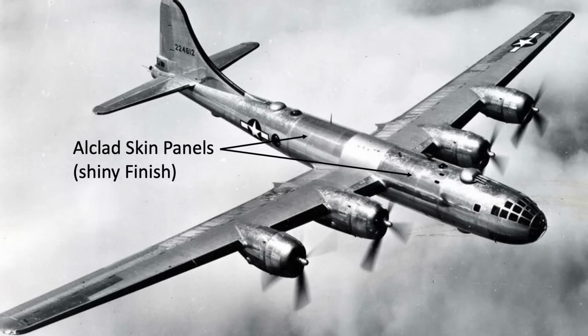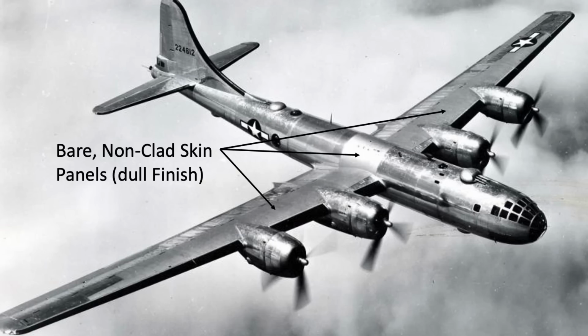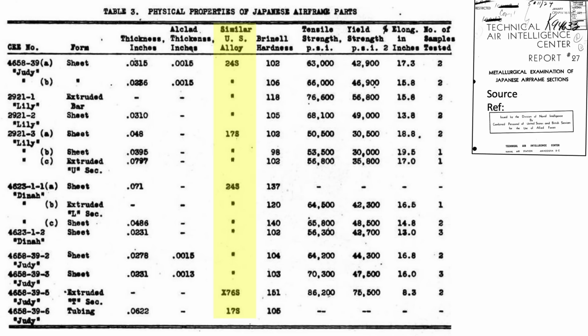You can tell an alclad finish by the mirror-like appearance, like the outer skin of this B29. Non-clad aluminum will be about 10% stronger than an alclad alloy and can be identified by having a dull finish, like these B29 fuselage center section skin panels. The remaining columns identify the similar U.S. aluminum alloy equivalent, hardness, tensile strength, yield strength, percent elongation or ductility, and the number of coupons tested.